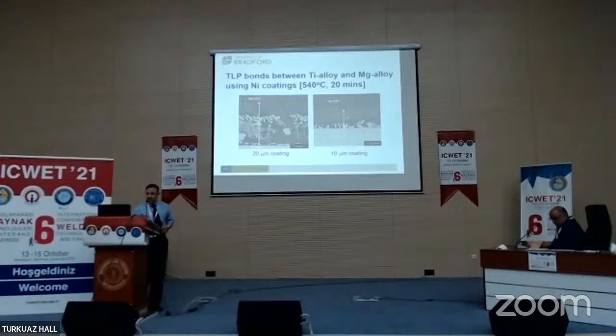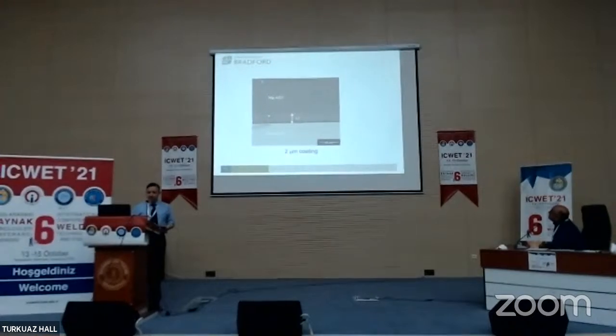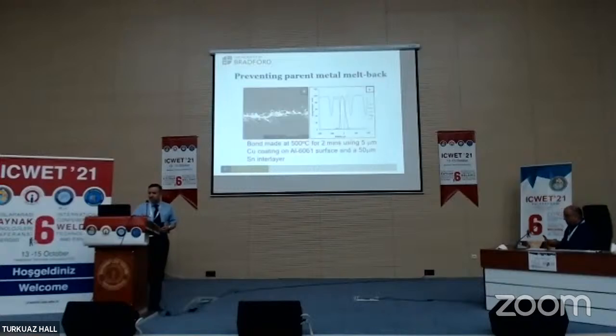If we look at some of these reactions here in these micrographs, we start with a 20 micron coating thickness, and this is 10 microns. Immediately, if you look at the volume of liquid formed, the width of the volume is much less for the same bonding time. And the amount of intermetallics is also less. So the thickness can have some control. And if we reduce the interlayer thickness to 2 microns, the intermetallics, the large ones, have partially disappeared. So this is a bond between magnesium and titanium. So interlayer thickness has some ability to control things.